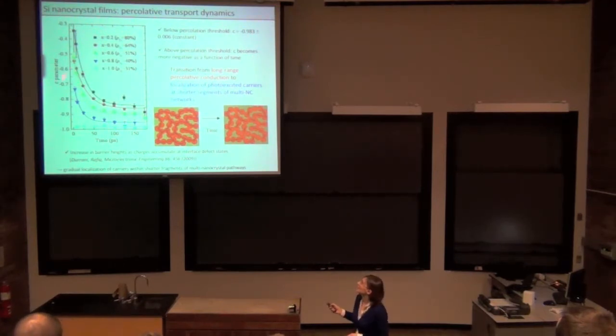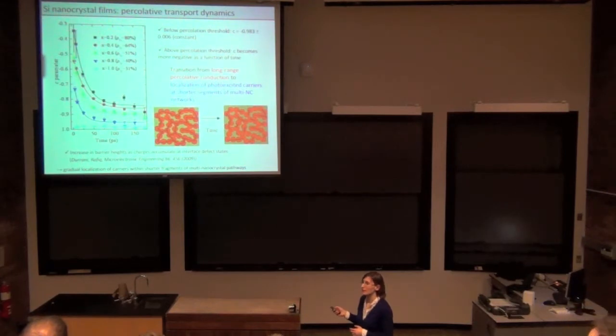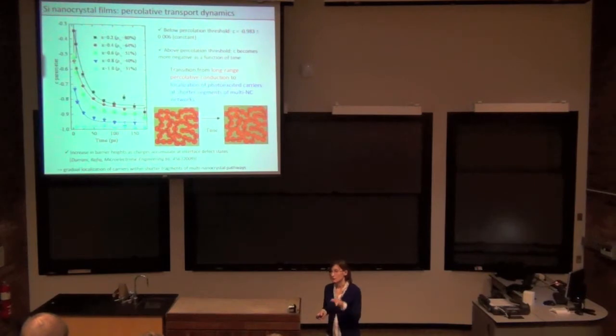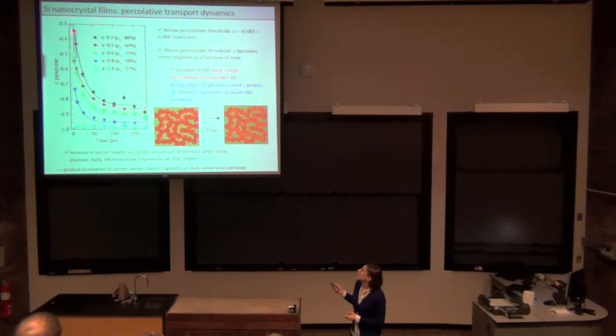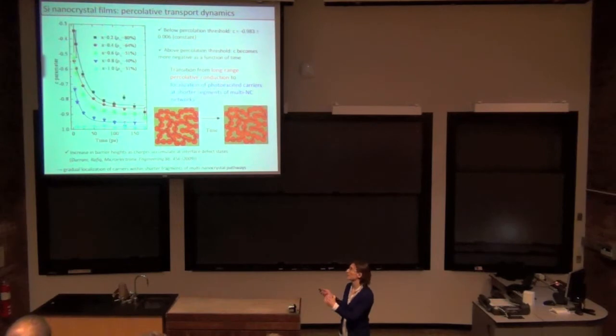I understand the first part of your question. The C parameter is actually what varies with time. So this is the time variation of the C parameter. We see everything else, like the scattering, staying the same. Of course, the number of carriers is decreasing because they're getting trapped. But the main change that we see is in the shape of the fitting curve, which is then reflected by the change in this localization parameter. This is what led us to believe that we're seeing a change from less localized to more localized transport.